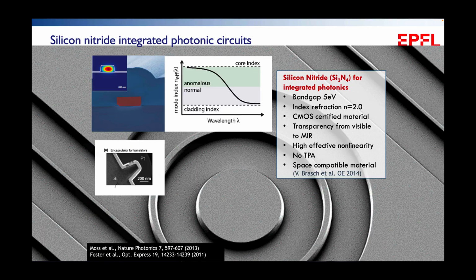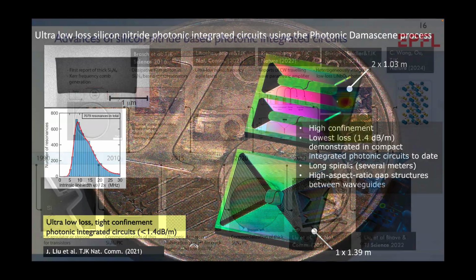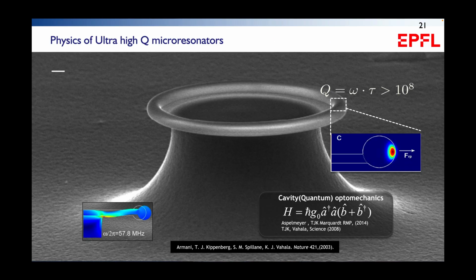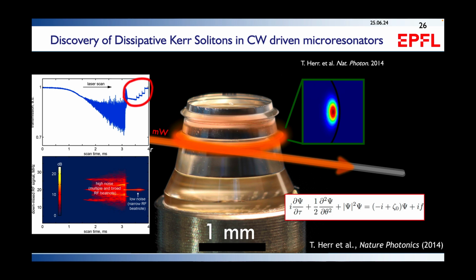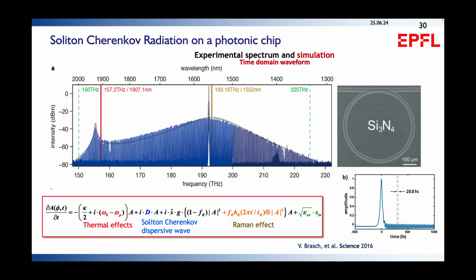Yeah, it's a very good question, an expert question. Your question was, first of all, about F-to-2F. One of the challenges, and still ongoing challenges, you can use the spectrum here as an example. You can generate octave spanning spectra in microcombs. The challenge is, first of all, you need power for doing F-to-2F. What you can do is use a so-called dispersive wave, which is a feature of the soliton, where the soliton has this oscillatory tail. You can engineer these to be exactly at F and 2F frequencies, and there's been work by Scott Papp at NIST that has beautifully shown that you can make octave spanning combs with F-to-2F aligned, and also Kartik Srinivasan at NIST in Gaithersburg.